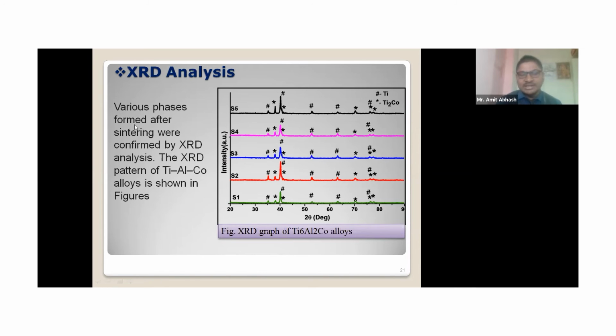So various phases formed after sintering were confirmed by X-ray diffraction analysis, and the X-ray diffraction pattern of Ti2CO is shown in the figure. This is the X-ray diffraction pattern of titanium 6 aluminum 2 cobalt. I have just taken the 2 cobalt because this is also the optimized data, and I have also varied the cobalt percent, and this I have published in Material Science Engineering A.